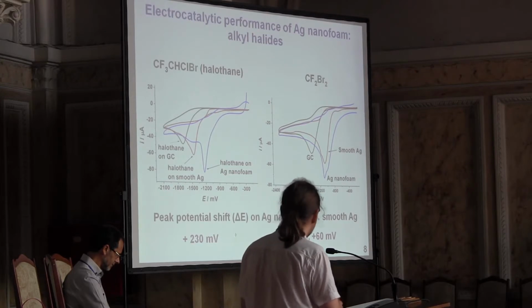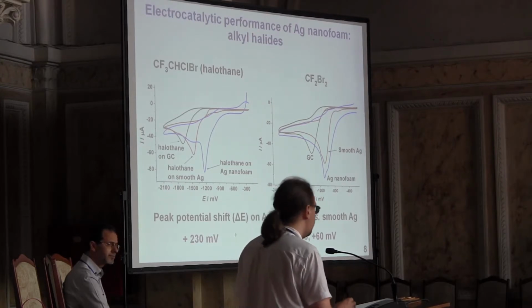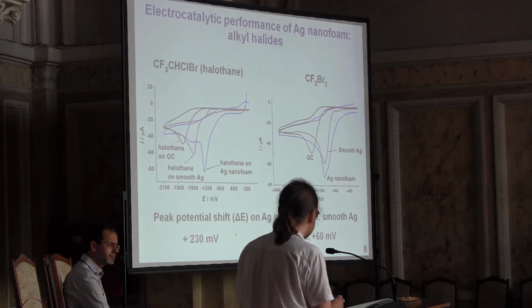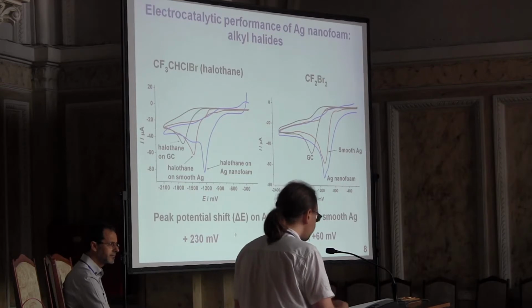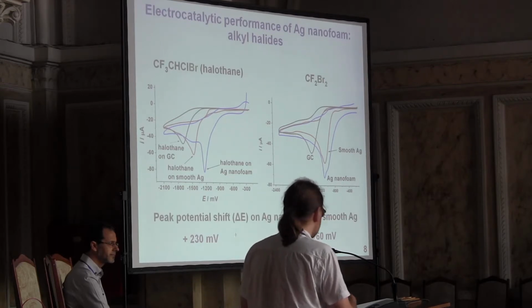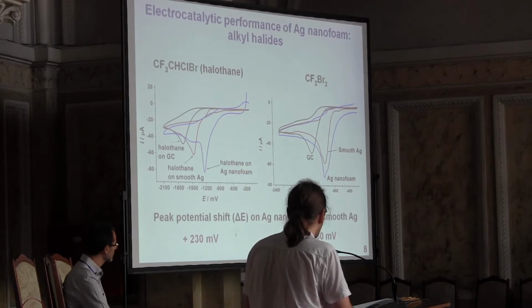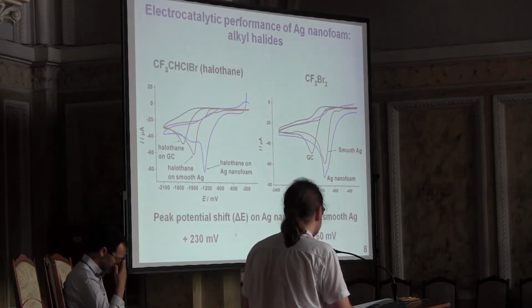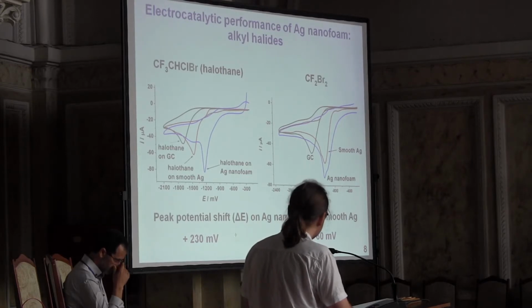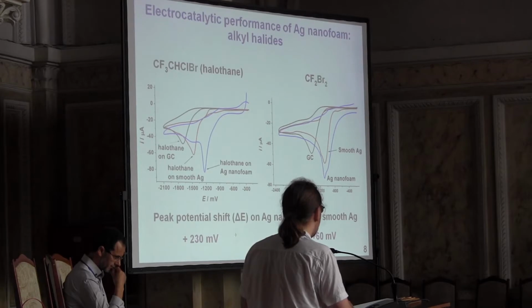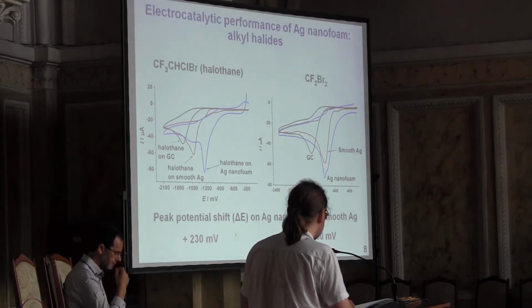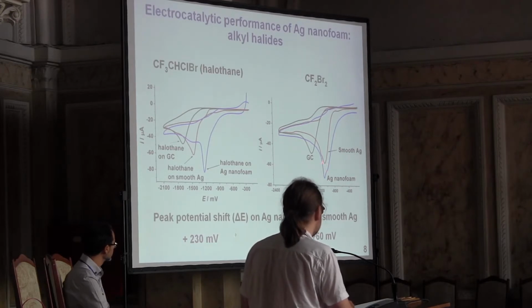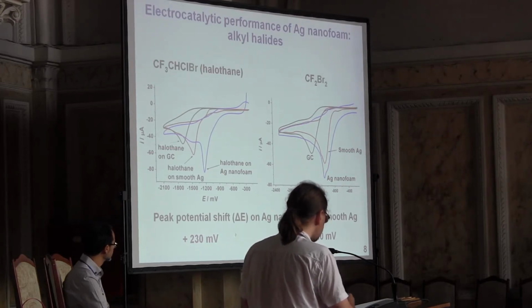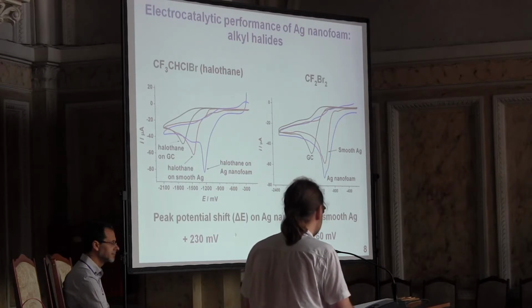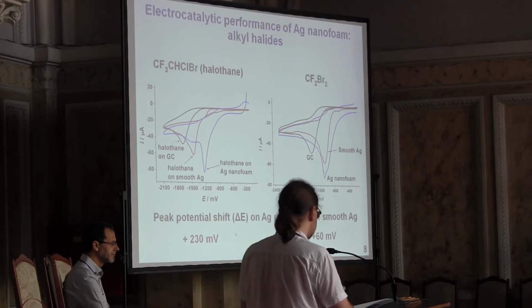Such results can be explained by formation of some kind of active sites in the nanopores of the silver nanofoam, which can promote the reduction of halothane more efficiently than the surface of the smooth silver. A similar situation took place in the case of dibromodifluoromethane, but in the case of this compound, the shift was significantly lower, and the potential at the peak at the potential similar to the potential of this process on smooth silver was significantly higher than in the case of halothane.